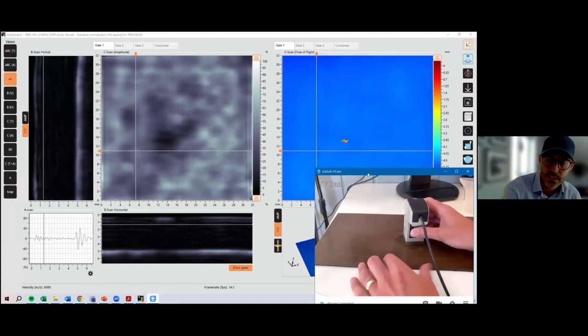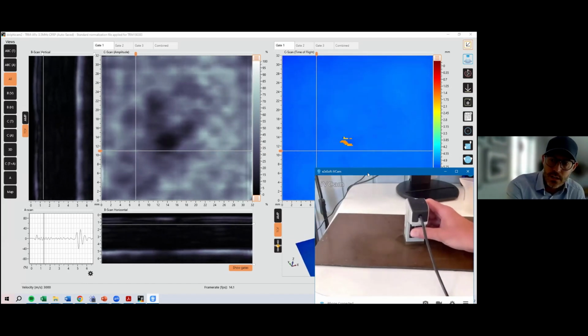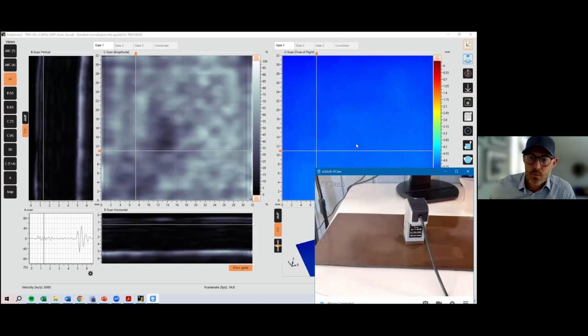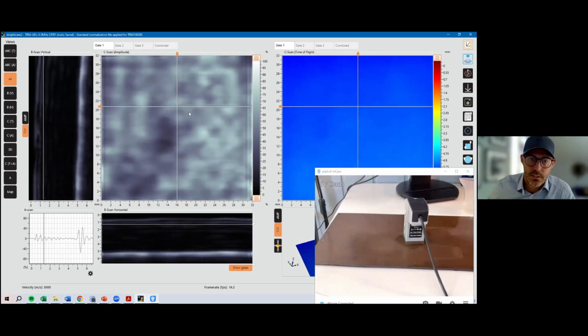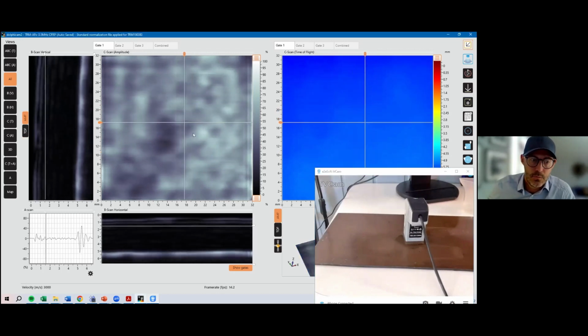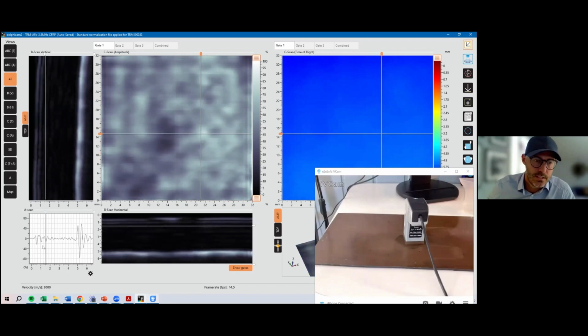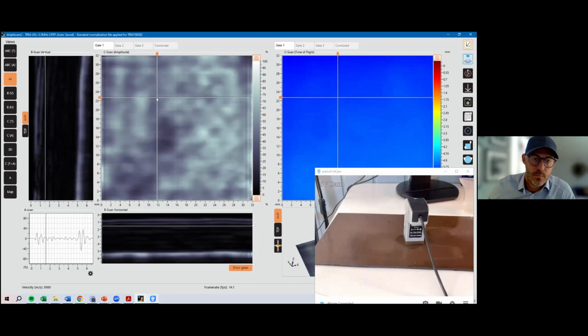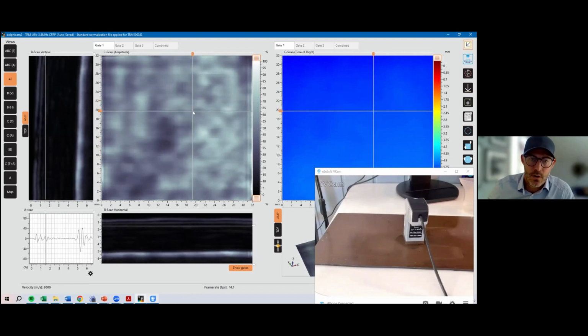So starting easily here now, I'm holding it over an area with no damage, right? So I can move this cursor around these two C scans here. I can move the cursor around, and you will see the A scan is moving depending on where I have my cursor. And the C scan that you have here, we have a C scan amplitude and a C scan time of flight. This C scan amplitude are values based on the amplitude of this pulse. So you see here, this amplitude is around 50%.